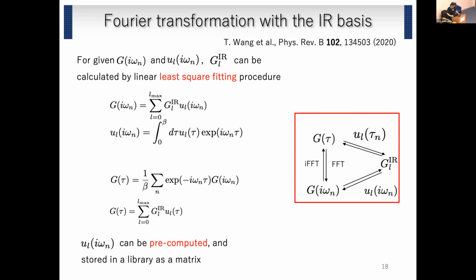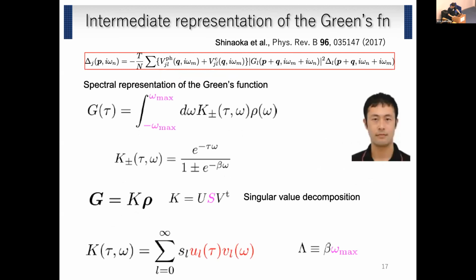Once we calculate it, we don't have to change it. So just keep it. And then, for example, we determine the coefficients of the Green's function. And once we have these coefficients, then using them we can calculate G(tau). So the calculation from G(i omega) to G(tau), or vice versa, can be done very effectively. And then using this fact, we can solve this equation very efficiently.